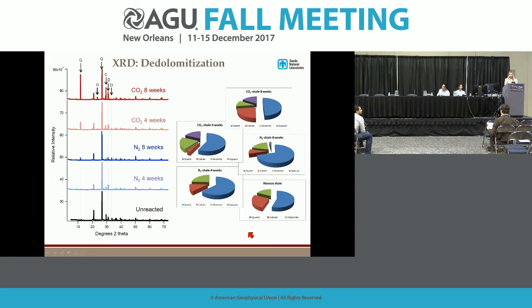And here I'm showing semi-quantitative results for the compositional changes. We're only quantifying major phases. There are many more than just three in shale, but those are the major components. Mancos shale was mostly quartz, calcite, and dolomite to begin with. In the control reactor, after 4 weeks, we saw some dissolution of calcite. And after 8 weeks, we saw further dissolution of calcite and a small amount of gypsum precipitating.